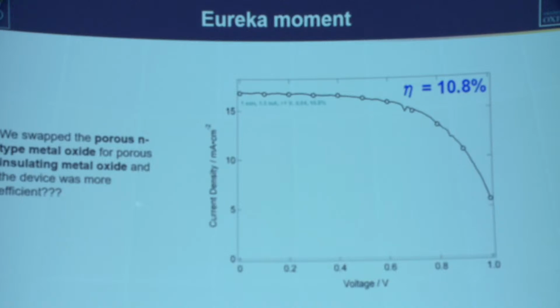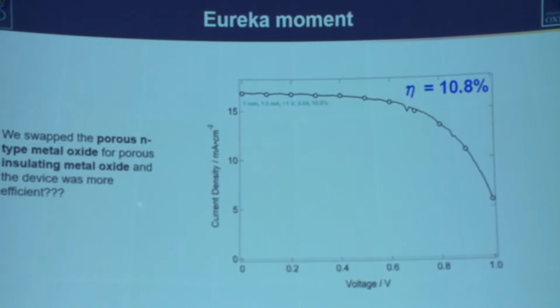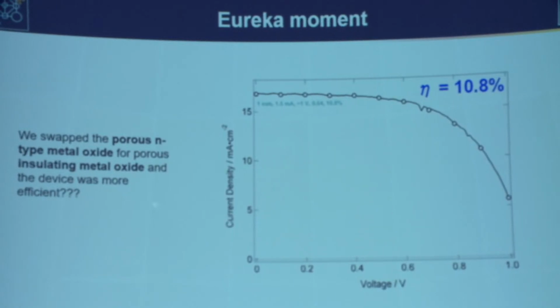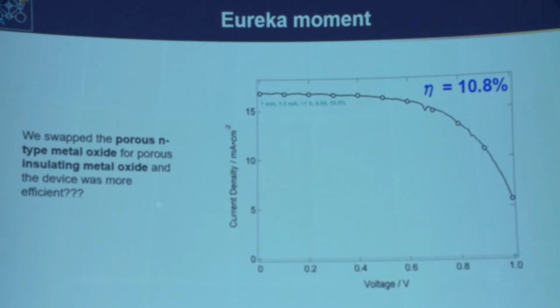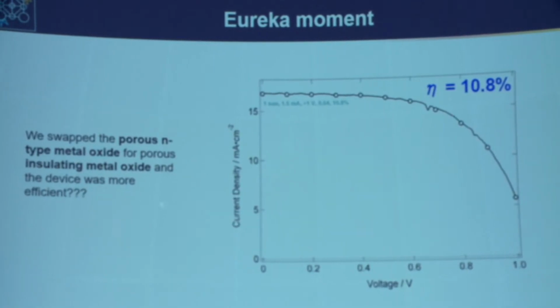So our first Eureka moment was Mike came back to Oxford and made some solar cells with the titania, and then we swapped the titania for porous alumina. Alumina is an insulator, and we just wanted to test to see if we had some conduction through the perovskite as well. He made two solar cells, and one of them was over 10% efficiency.